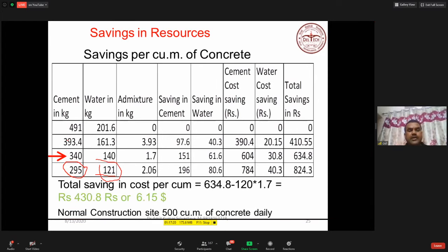So now if I compare from 490 to 295 kg, I can reduce the OPC requirement by 196 kg, and I can reduce the water requirement by 80.6 kg. This is about 40%. But our IS code says that you cannot use cementitious material less than 340 kg for M35 grade of concrete. So if I am restricting myself as per the IS code's durability requirements, then I will use 340 kg, then the reduction will be like this 140, and I will be using 1.7 kg of the admixtures.